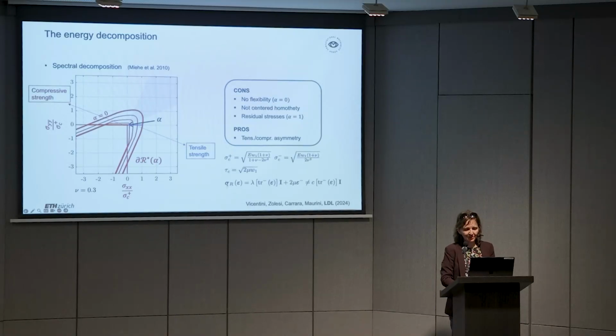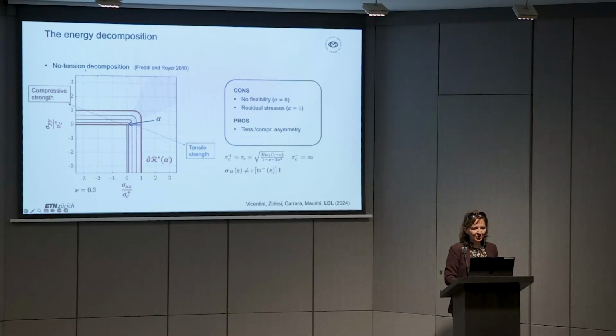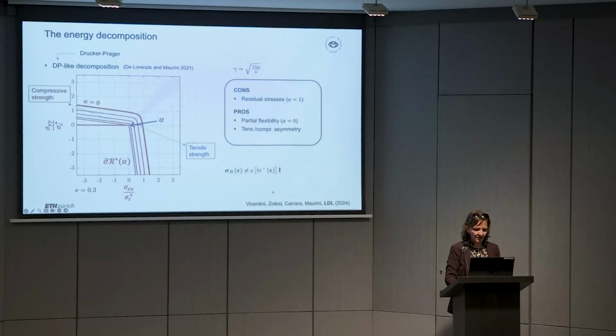But the really bad property of this model is that it doesn't have a good residual stress. So this is the reason why the block under shear was not working, was giving us spurious stresses. And if you look at the no tension decomposition, this is called no tension, in fact, because the compressive strength is infinite. So here the plate with hole works perfectly, the compressive strength is infinite, so you don't have any competition anymore, you can only nucleate in the right, proper way, but the residual stress, again, is bad. So this is why this didn't work well in the sliding block example.